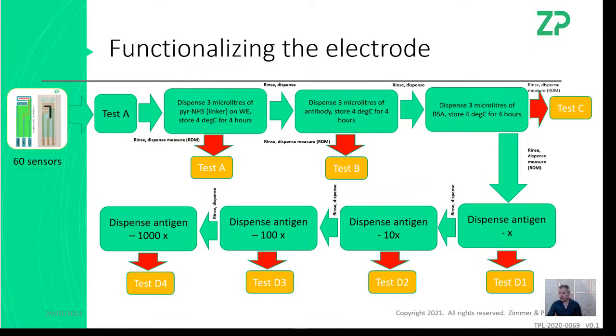We tested them again. We did the antibody. We tested them again. We put the blocking agent on, we test them again. So we're testing them at every stage to make sure that every stage is working. I mean, you should see a fairly significant change in the cyclovoltammetry every time. And then we actually do the actual testing itself by putting the antigens on.